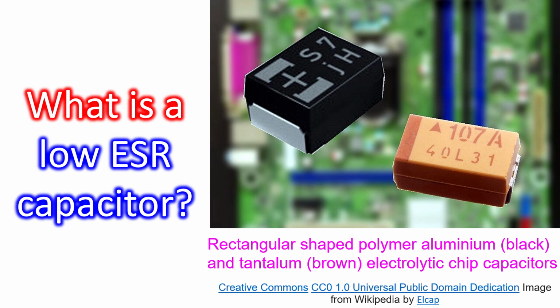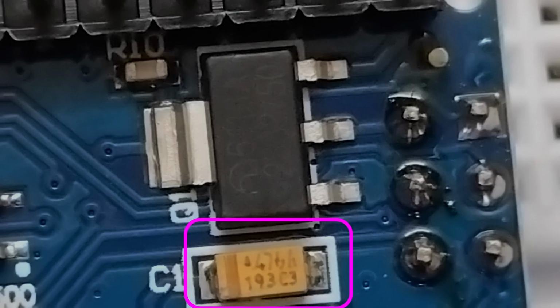In non-electrolytic capacitors, the resistance is a combination of that offered by the leads and several mechanisms in the dielectric material. In case of electrolytic capacitors, resistance offered by the electrolyte also comes into action. Ceramic capacitors have ESR in the range of 0.01 to 0.1 ohms. Aluminum and tantalum electrolytic capacitors with non-solid electrolyte have much higher ESR values of several ohms.